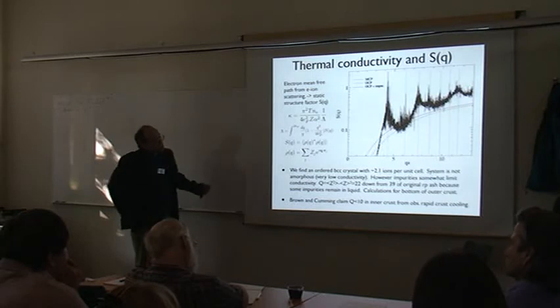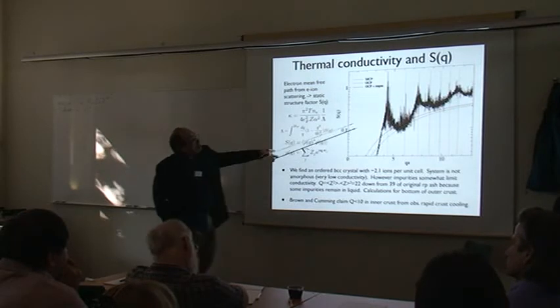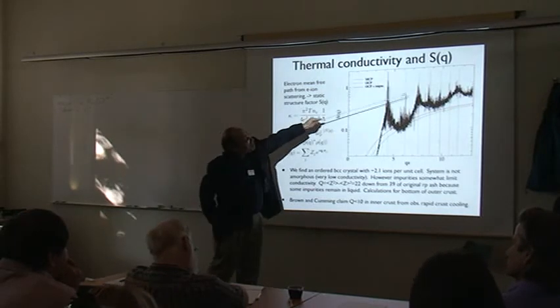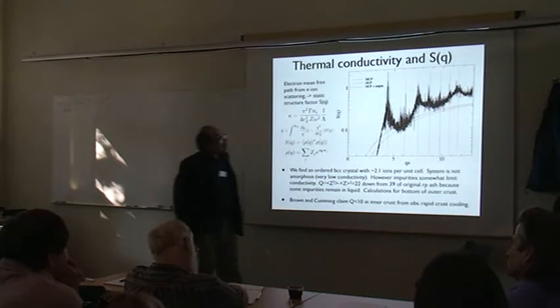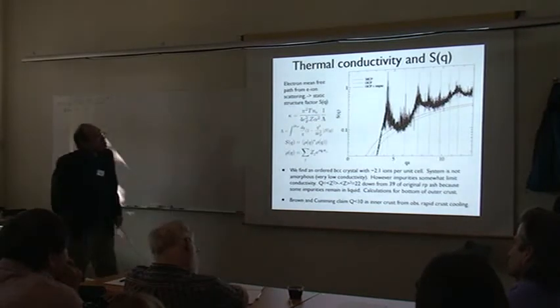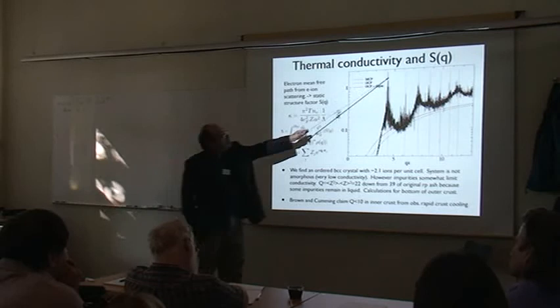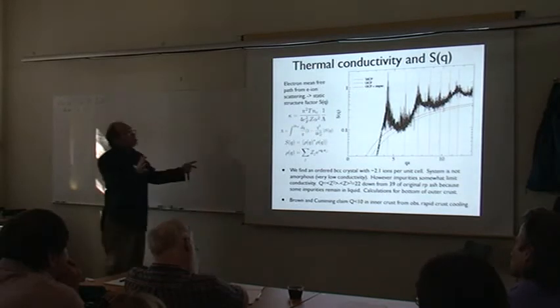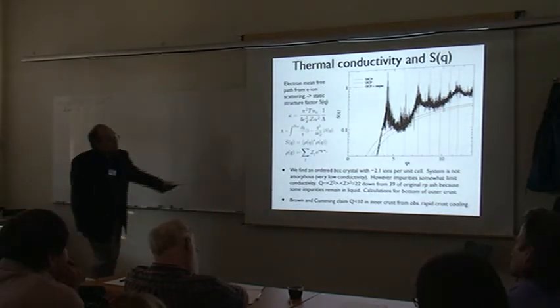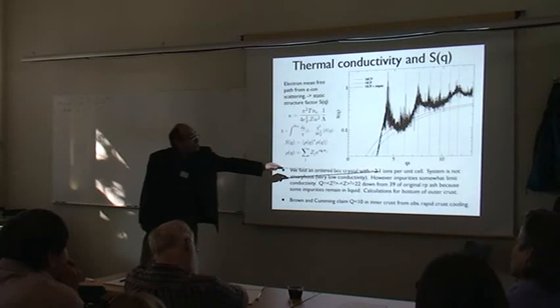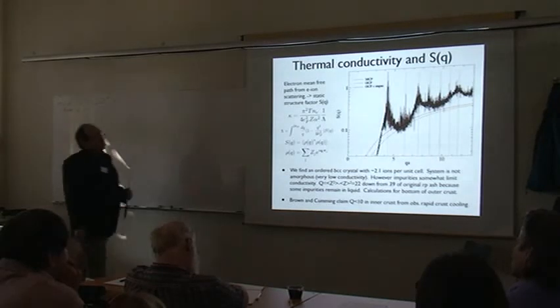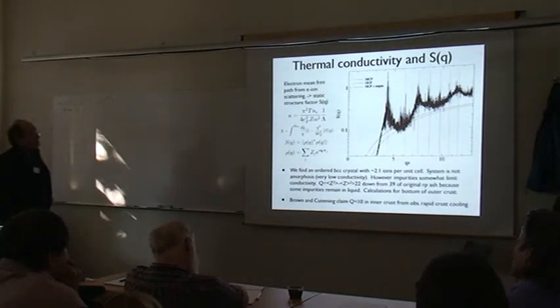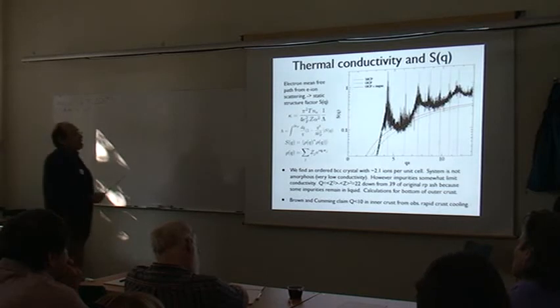And actually the crystal does have spikes. The spikes are near the Bragg peaks, but they actually happen at slightly lower Qs. So the unit cell is just a little bit bigger—in fact, there are 2.1 ions per unit cell rather than 2 for a normal BCC lattice. So you have a few impurities in interstitial sites; they slip in between the lattice sites.